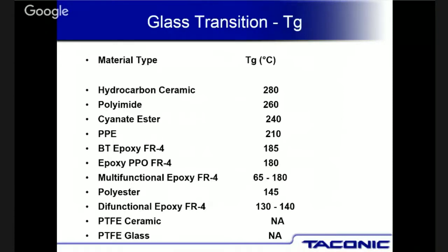By the way, if you look at it, all those materials on the top are, I'm going to say, more exotic materials. Typically, when we're building boards, your typical FR4 materials, you're looking at multifunctional epoxy or difunctional epoxies. What they have, you look over here and you'll say 130 degree T sub G or 140 degree T sub G. That means that the material has a linear expansion up to that point. Then above 130 degrees, the expansion goes up very, very significantly, like 5 times. What does that mean?